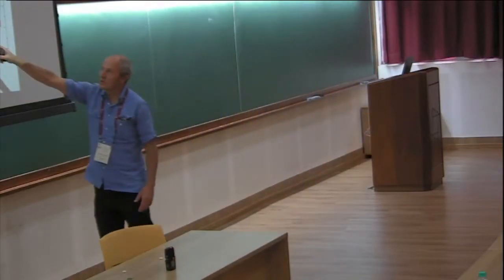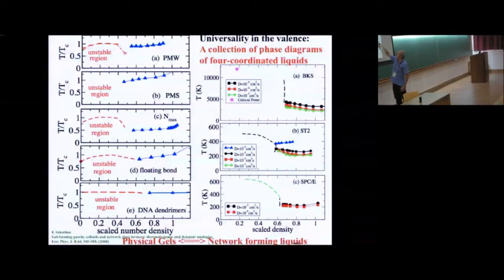Those lines that you see here are lines where the diffusion coefficient is the same, and in this phase diagram they are quite flat. That tells you that density doesn't really play an important role, and the dynamical arrest is essentially controlled by temperature. Why is this happening?